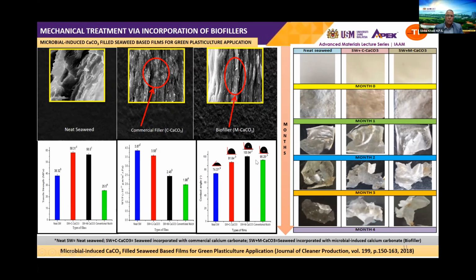This is due to the good compatibility between matrix and the biofiller that makes the stress transfer from the matrix to the filler more efficient, thus improve the properties of the seaweed biopolymer. Figure on the right shows the seaweed-based composite films incorporated with biofiller show higher degradations than those with the commercial one. And this result has been published also in the Journal of Cleaner Production in 2018.